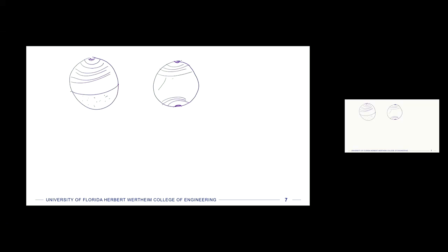So if we look at a cross section of bending in one direction, it kind of looks like what I drew before, right? It would have its initiation and then the beach marks, right? And then eventually it might have just a rough surface where it fractured at the back. If it has reverse bending, then we know from thinking about this that it's going to have a maximum and minimum stress that totally reverses. So it might have an initiation on one edge, and then shortly after that might have an initiation on the other edge, right? Because the stress is reversing from top to bottom, and then eventually it will break apart,